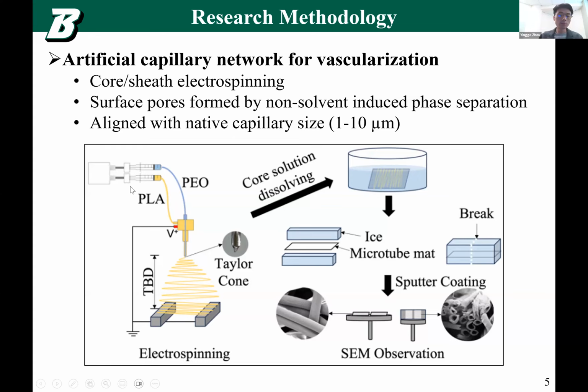The materials we use are PLA and PEO. They are both biocompatible polymers, where PLA is not dissolvable in water and PEO is dissolvable in water. So we can dissolve PEO in water and PLA in another organic solvent and then put them in the syringe in a core-shell manner. When they extrude out, we get core-shell fibers. Because the core is dissolvable in water, after we collect the fibers, we put the whole sample into water for water immersion to dissolve the core. Therefore, we got the tubes instead of the fibers.